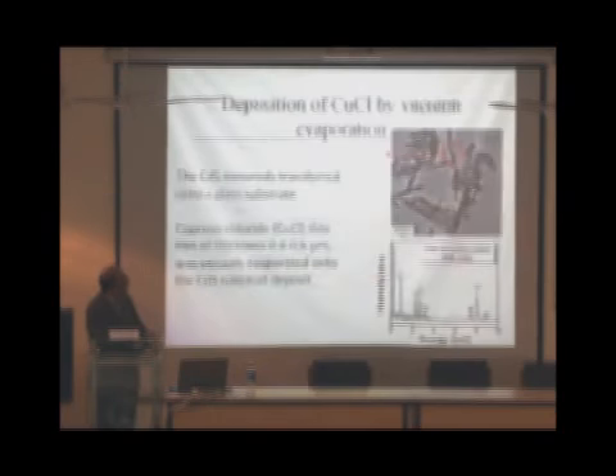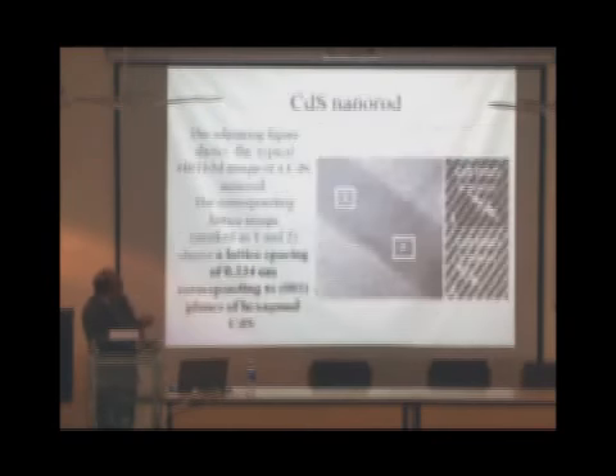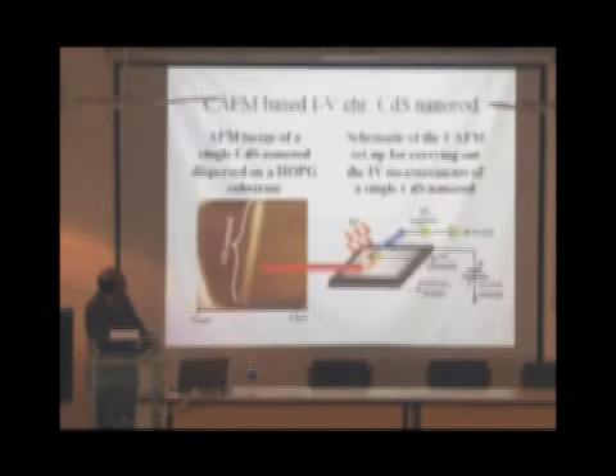So we are able to form a heterojunction within a nanorod by using a very simple chemical reaction. You can see that this is one of the cadmium sulfide nanorods where copper chloride powder is deposited, and this is a high resolution transmission electron microscopic picture of one nanorod of cadmium sulfide. You can see it's very high quality, monocrystalline in nature, and this is where we have been able to convert part of that nanorod into material B, copper sulfide, and there is a junction. And this junction we could investigate using a conducting atomic force microscope.